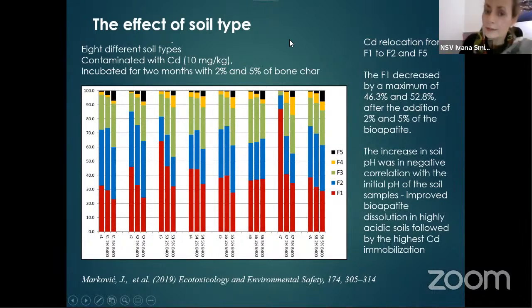Then we have investigated the effect of the soil type on the efficiency of remediation. These are the results from our group. They are performed using 8 different soil types, which are characteristic for the Republic of Serbia. These types have very distinct physical-chemical properties, and we have contaminated them with the same level of cadmium and introduced 2% or 5% of the bone char. And after 2 months of incubation, the sequential extraction of cadmium in the soil was performed.